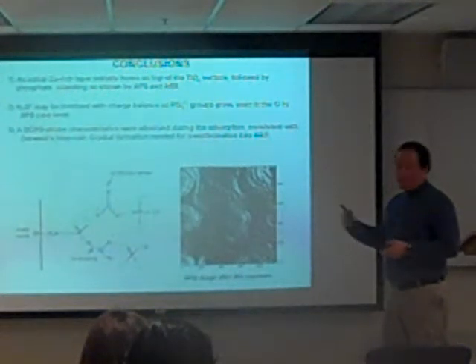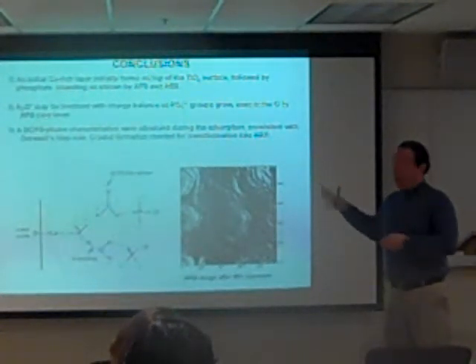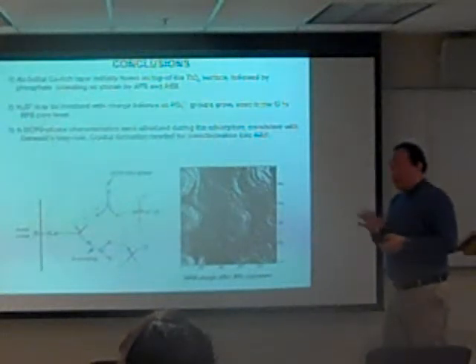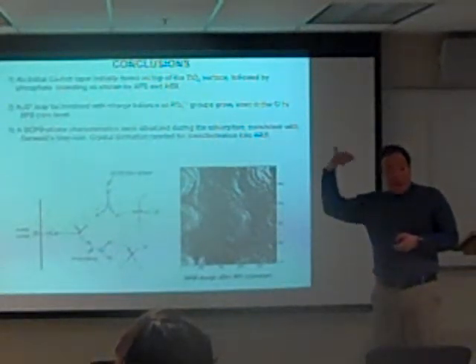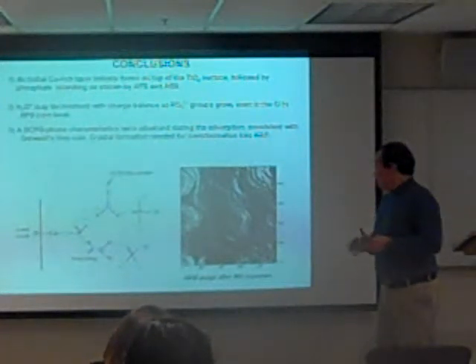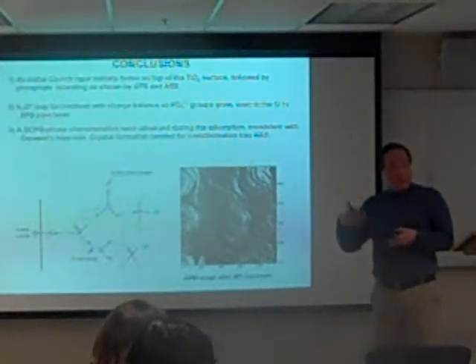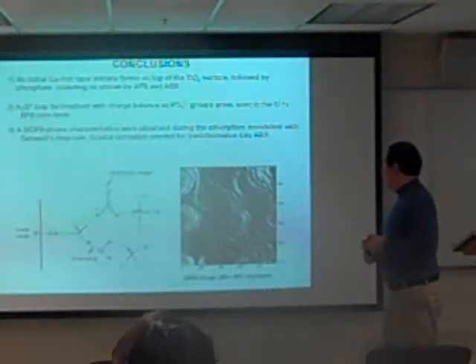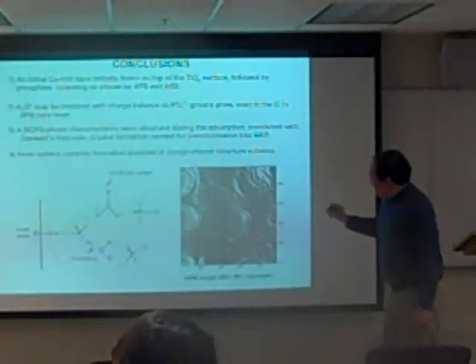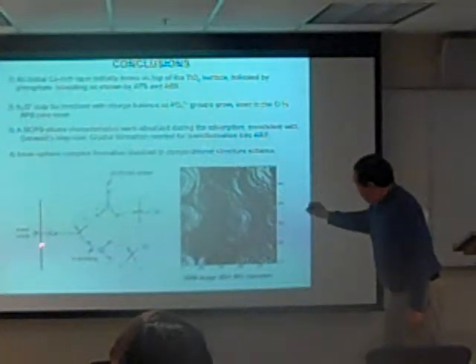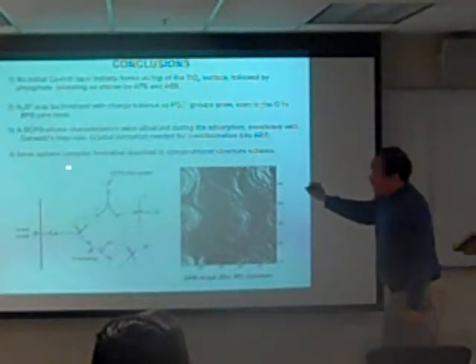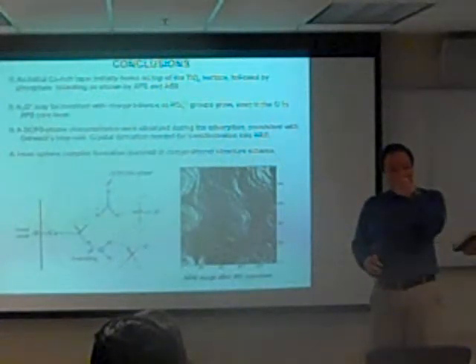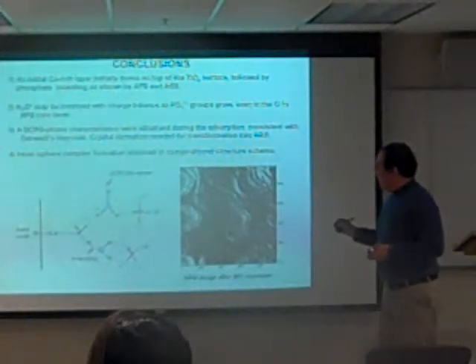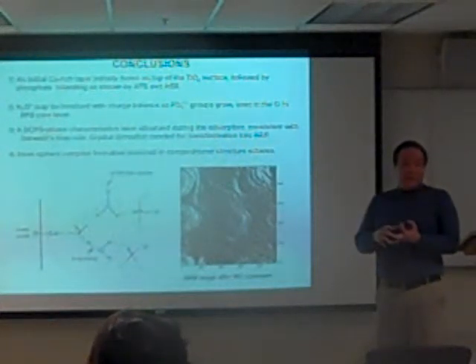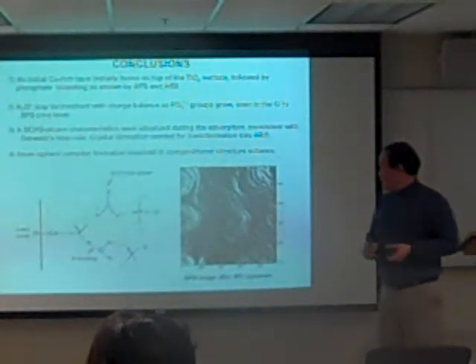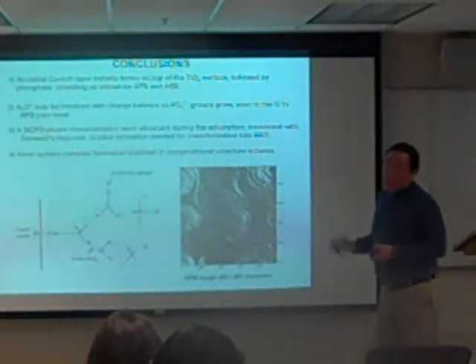So we don't see hydroxyapatite immediately form, but this is a very early stage of nucleation growth. It turns out that in the next part of this talk, you see that it requires much longer exposure times to form that phase that we find in bone. And another thing is that in doing this scheme, I basically borrowed some ideas from inner-sphere complexation, that geochemists or geologists use, where materials bond onto those sites of, let's say, a mineral oxide. So that's where this scheme comes from.